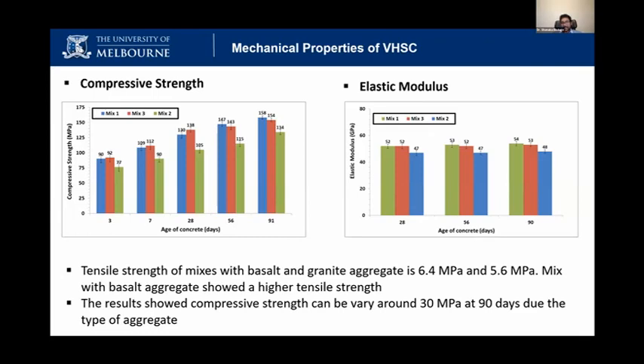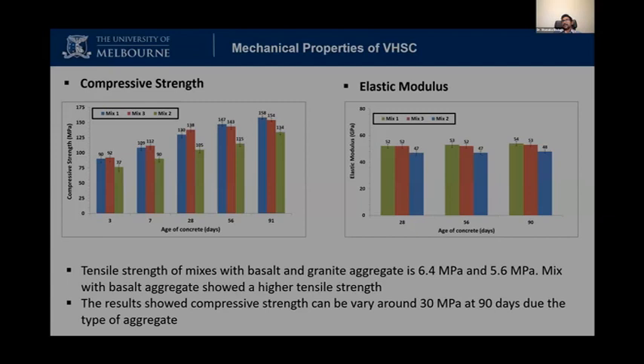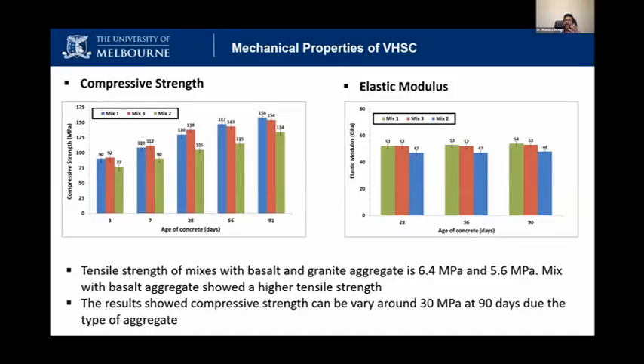Because we know that silica fume and slag reactions are a bit slow. The silica fume and fly ash react with the calcium hydroxide, and the slag also has cementitious properties because of the calcium oxide within it. So it is better to give some time and probably target the mix for 56 days. But we found that around 28 days, it achieved 70% of its strength, so there's still 30% that we can gain. Then the elastic modulus was very consistent, even with time, more than 50. We achieved somewhere around 52, 53 gigapascal.